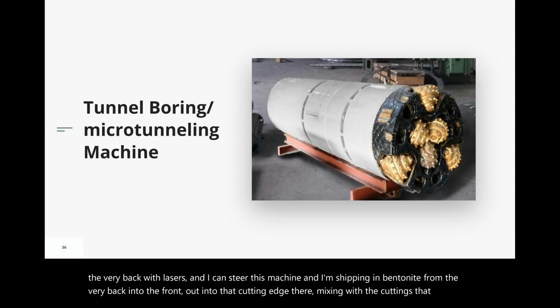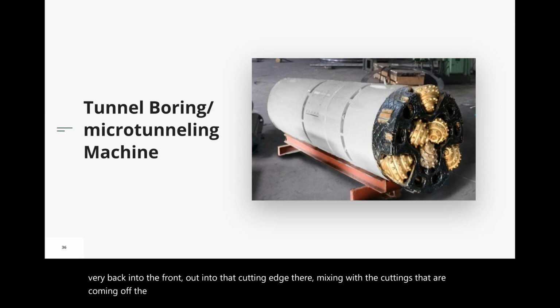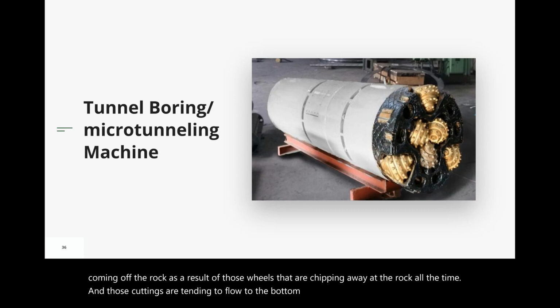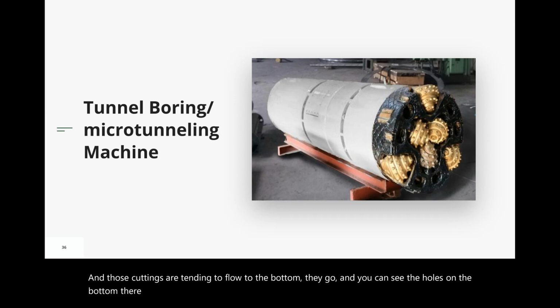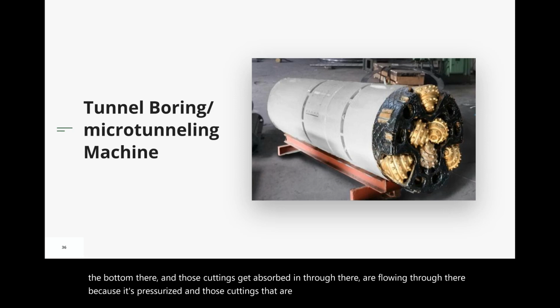Here's a large tunnel boring machine. Now, we just talked on the micro tunneling machine. As we talked the pipe jacking, we're limited, as we said, to 80, 90, 100 meters because we're pushing the pipe from the back. Now we get into a tunnel boring machine, we do not push the pipe from the back. Once the pipe is put in place, it is not moved anymore.